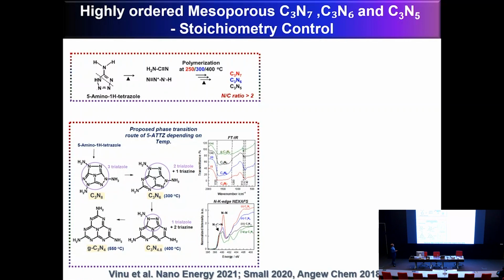But can we do it without changing the chemistry and make the material with a different carbon to nitrogen ratio? So in this case, what we have done is we use the tetrazole as a precursor. That's a cyclic molecule with 4 nitrogen atoms and 1 carbon atom, right? And it easily undergoes decomposition to get the cyanamide and then hydrazoic acid. That undergoes polymerization at different temperatures. You can get carbon nitride with the C₃N₅, N6 and N7.